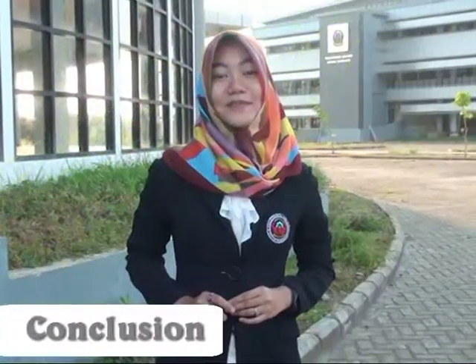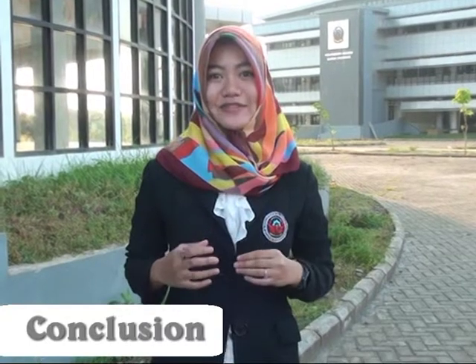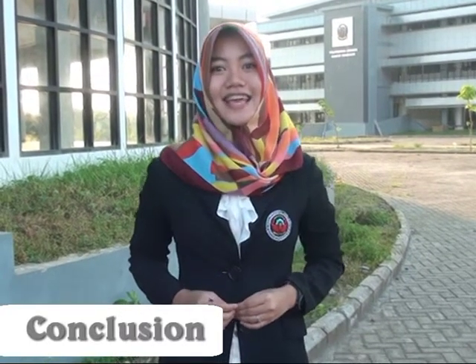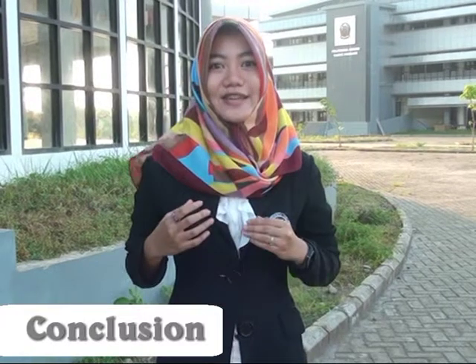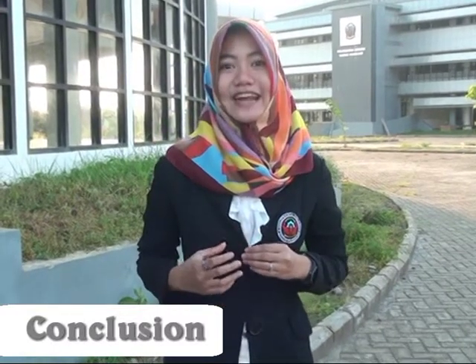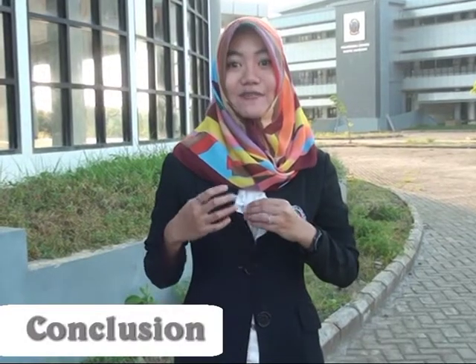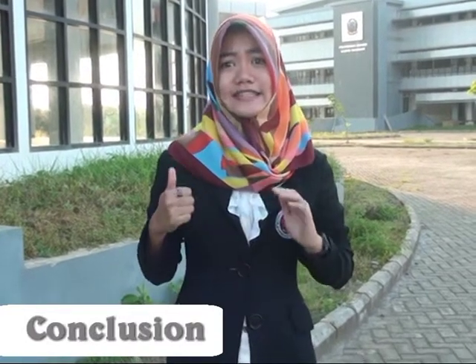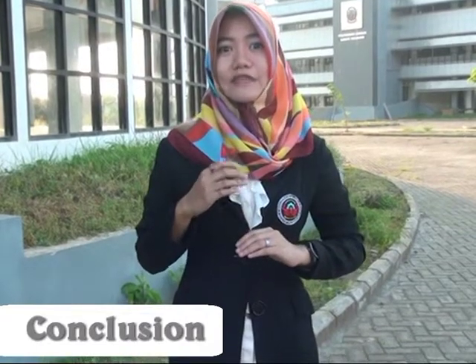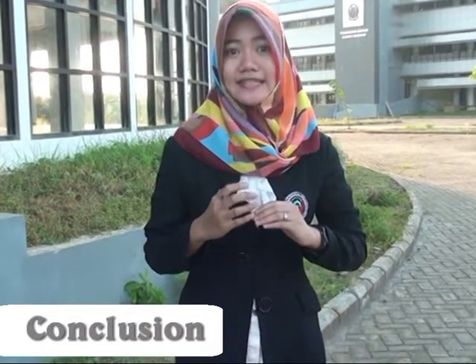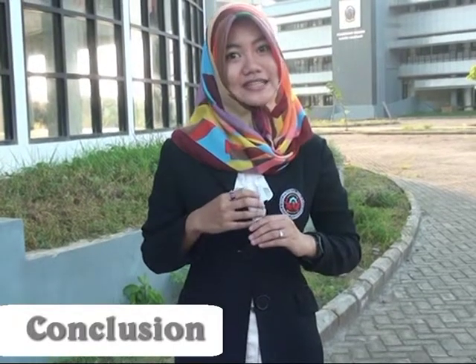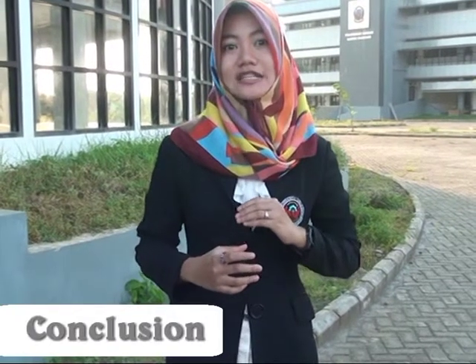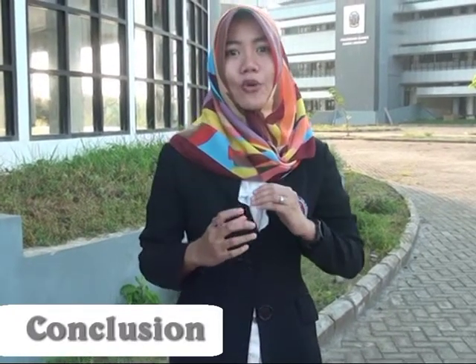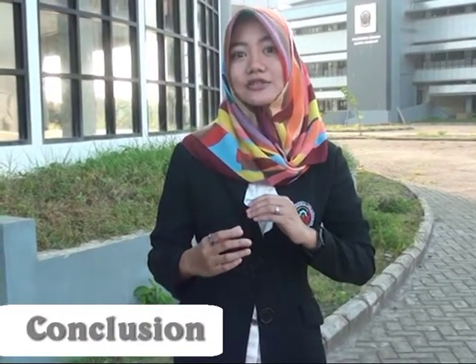Conclusion of my scientific paper. From the results of research on mild steel corrosion testing that has been done, it can be concluded that the extract of aloe vera can be used as a corrosion inhibitor of mild steel in immersion for 6 days, or 144 hours, in 3% natrium chloride medium or artificial seawater. Mild steel corrosion rate without the addition of inhibitor solution, 0%, was 23.59 microgram per centimeter squared hours.